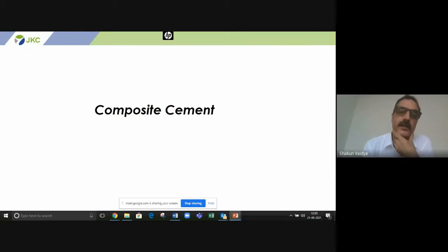The latest variant in this category is composite cement. PPC and PSC are known to everyone, and were introduced long back. Now 3-4 years back, this new variant of blended cement, composite cement, was launched. Though it is not available in this part of India, northern India, it is becoming very popular in East India, where it was launched around 3 years back, when the BIS permitted the use of composite cement and the code was also released. But since we do not have slag here in north and west, producing composite cement as of now is a challenge. But this is one of the very futuristic blends of cement, which uses fly ash as well as slag simultaneously with Portland cement.